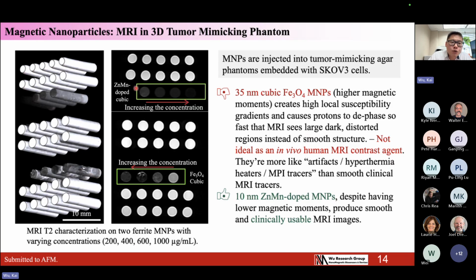On the other side, for the 10 nanometer zinc manganese doped MNPs, the imaging is very smooth compared to the bottom one. The MRI imaging is very smooth, which gives you very smooth or evenly distributed particles in the space, which is the ideal case for MRI imaging and hyperthermia treatment. So here I showed you that these particles are capable of MRI imaging and also capable of hyperthermia treatment.